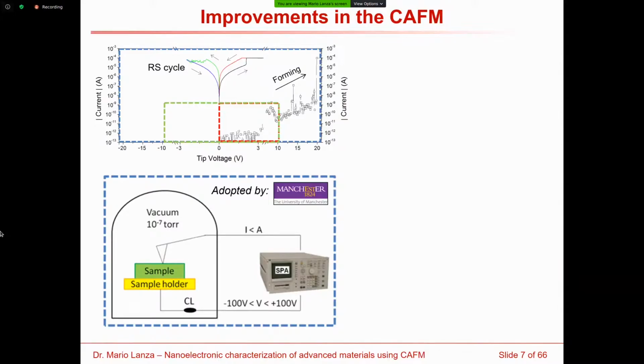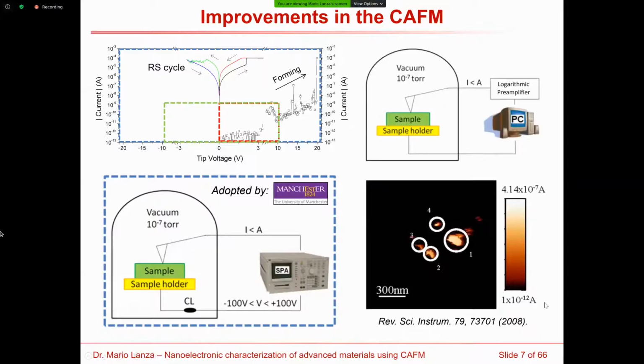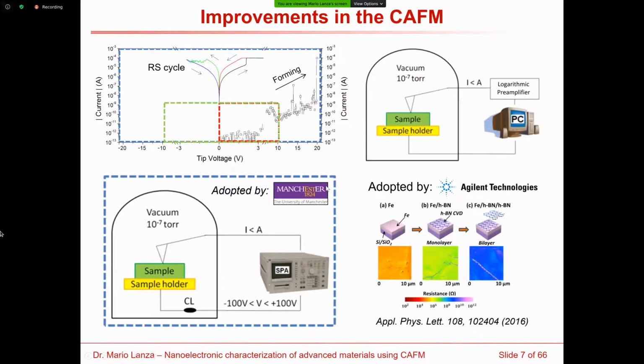However, I have to say this has one important problem, which is this setup can only be used to apply ramp voltage stresses in one specific location. The tip cannot be moved laterally because coordinating, synchronizing the semiconductor parameter analyzer with the vacuum, with the movement of the tip is really complex. So in order to solve this problem, what we did back in 2008 was to fabricate one logarithmic preamplifier that can convert the signals very fast, much faster than the SPA. And for this reason, this can be used during the lateral movement of the tip. Thanks to this setup, we created the first current maps with multiple orders of magnitude in the current scale, as you can see here. And our setup was later commercialized by companies like Agilent Technologies, and right now is being commercialized by Park and by other companies.